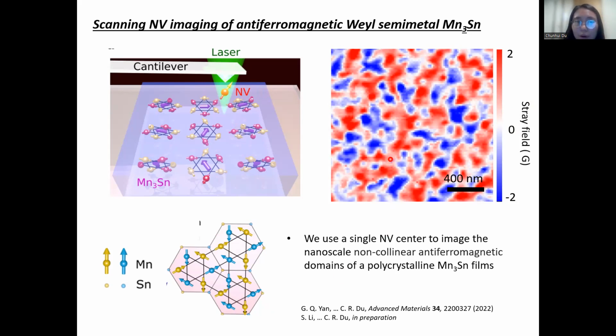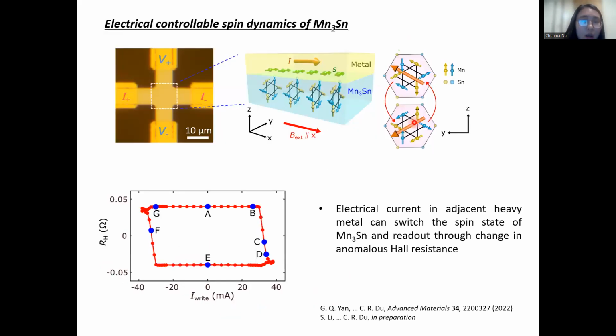Then we will monitor the electrically controllable spin configuration of the Mn3Sn. So we pattern the device into a Hall bar structure, and then we send the current into the heavy metal grown on top of the Mn3Sn. And this will lead to switching of the magnetization of Mn3Sn that can be read out from the variation of the anomalous Hall effect. So from the anomalous Hall effect, we can see that indeed the spin states of the Mn3Sn are switched between two states.